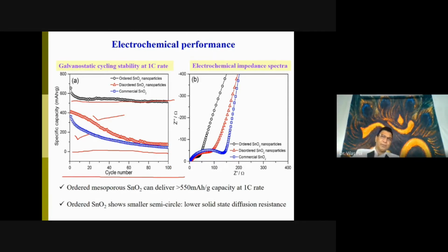That's why the nanomaterials could be bad or good for the battery application based on how you design them and how you are utilizing them. This impedance spectra tells you about the conductivity or the resistance in the system. As you can see, the ordered tin oxide particle has a low resistance. This half circle is very important. If it is smaller, that tells you the impedance or the frequency. Smaller the better. On the contrary, the commercial had the bigger channel and the lithium diffusion was a difficulty. And that is the reason the battery could die faster.